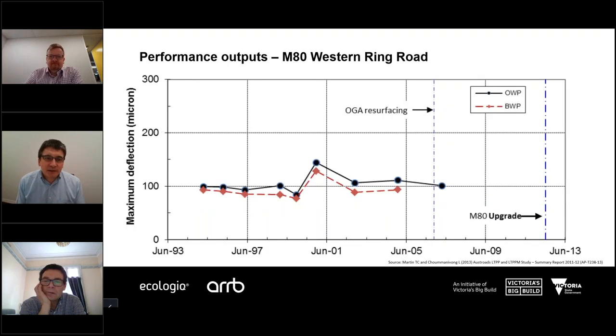The next slide shows the stiffness of the pavement. Now, Michael Moffat mentioned the importance of stiffness in a pavement design and in its performance. In this case, we're measuring stiffness using a falling weight deflectometer and measuring the deflection of the pavement. And the graph shows the progression of deflection over the first 10 years of life prior to the upgrade of the M80 and the widening. The data shows a maximum deflection of 100 microns or 0.1 of a millimetre.